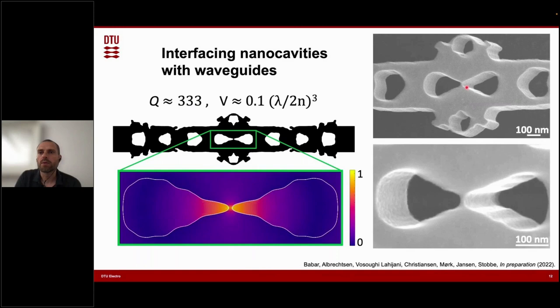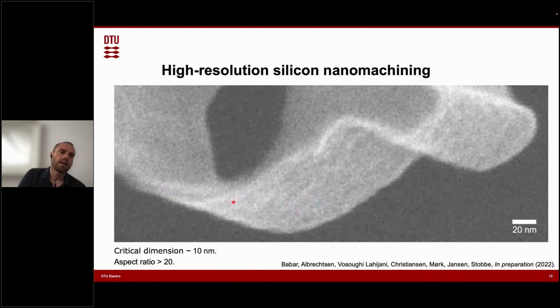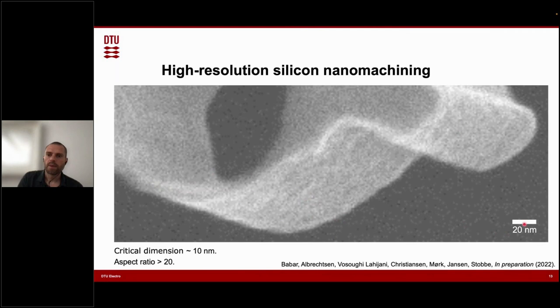This is what this structure shows. Here you can see the electric field, you can see what it looks like coming out of the clean room. I do want to stress that some of these features here are actually extremely small. I actually provided a zoom in of some of the smallest features in this design, which is on the next slide. This is now approximately 10 nanometers. And it's really impossible to make a claim about the size because, as you can see, even though our SEMs are pretty good, the scale bar is pretty crazy and it's really hard to make any solid claims. But I think this is ballpark 10. There's some SEM bloom, which is well known, that makes things look a little bit larger than they are. But it's really hard to say. So it's sort of ballpark 10 in this device.